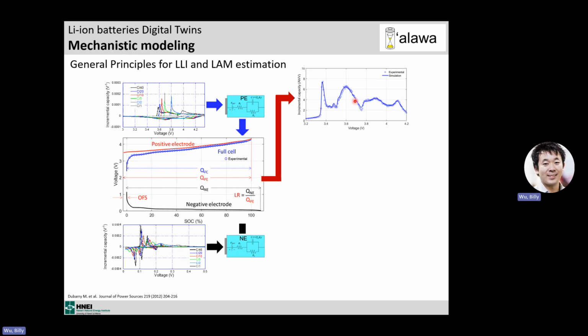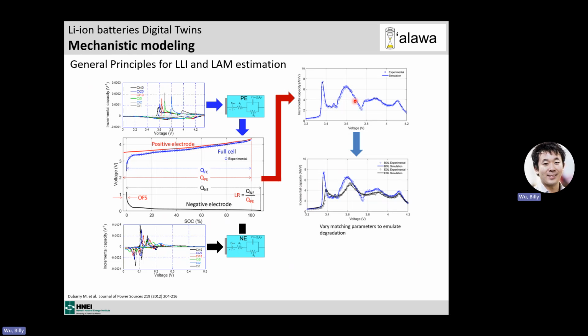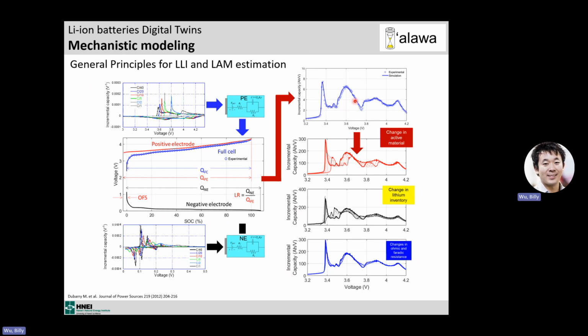And we can do that fit at beginning of life, and we can do the fit at end of life. And how the parameters changed, that's how the cell degraded. And we can relate that to the change of active material, change of lithium, change of kinetics, because we can decompose each and every one of them individually. And that model is really fast. We can do hundreds of thousands of simulations a second without a problem.